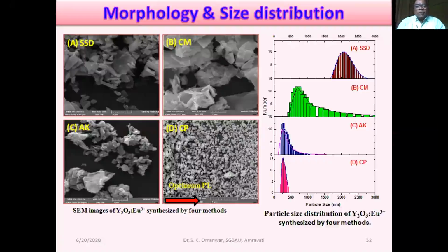And if you look at this combustion synthesis, you will see that the particle size is getting reduced. But there is also the possibility of getting larger particle sizes. Here the distribution is narrow. The aldo-keto method gives you very good particle size, and the photoluminescence of the aldo-keto product is also comparable with the co-precipitation. But here the full width at half maximum, if you calculate, the particle size distribution is wide. Whereas the co-precipitation method gives a narrow distribution. Most of the particles are of equivalent size, and that is why we can say that the co-precipitation method gives you the optimum here.